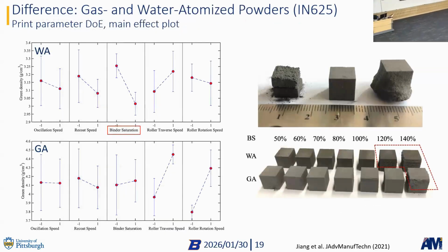As I mentioned, we were very naive in the beginning, and so we just followed the printing parameters that the binder jet printer manufacturer gave us for these materials. That's usually a bad idea, okay? Don't do that. It's a good first step, but then you need to actually figure it out. So next we looked at how the print parameters actually affect the green density, because we want to get this as high as possible.